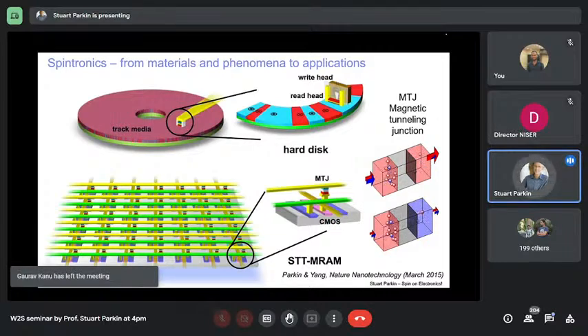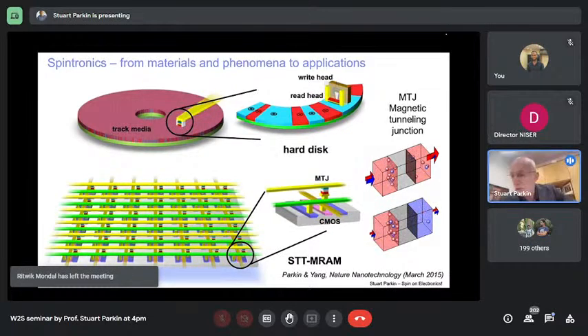So we proposed in 1995, which is 27 years ago, we could build a very interesting memory using magnetic tunnel junctions. And originally, we proposed that these would be switched by magnetic fields we would create by passing currents through bit and writing lines. And the bit lines and writing lines are shown in this cartoon. So basically, this device is very similar to many CMOS memories in that you have a so-called cross-point array. You have a series of parallel electrodes and another series of parallel conducting wires perpendicular to the first set. And at the intersection between a bit line and a write line, we place this magnetic tunnel junction, so the current flows perpendicularly from one line to the other, basically vertically through that structure.